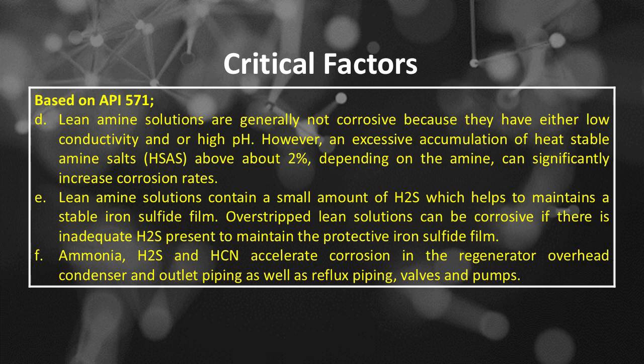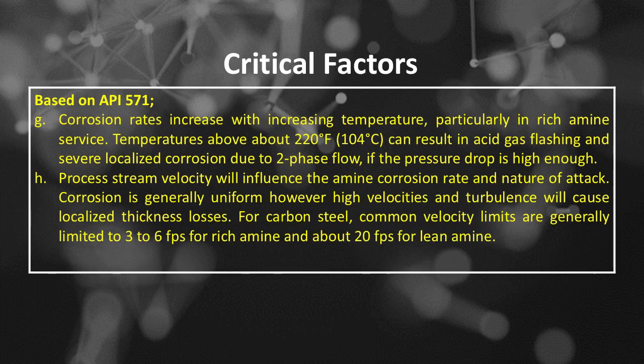Number F. Ammonia, H2S and HCN accelerate corrosion in the regenerator overhead condenser and outlet piping, as well as reflux piping, valves and pumps. Critical factors. Number G. Corrosion rates increase with increasing temperature, particularly in rich amine service. Temperatures above about 220 degrees Fahrenheit (104 degrees Celsius) can result in acid-gas flashing and severe localized corrosion due to two-phase flow, if the pressure drop is high enough.